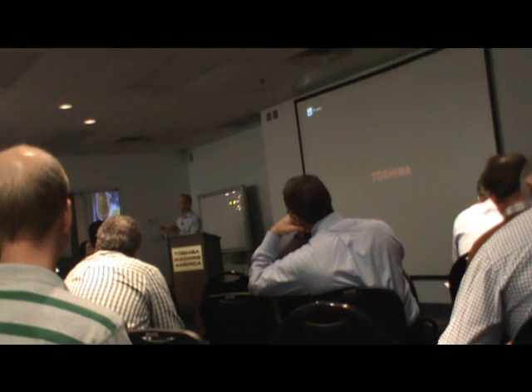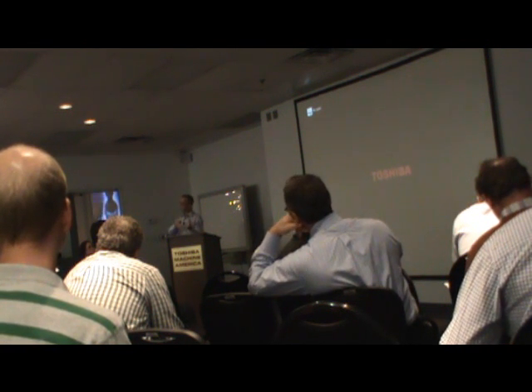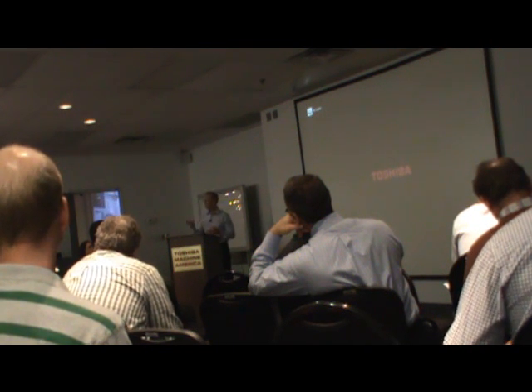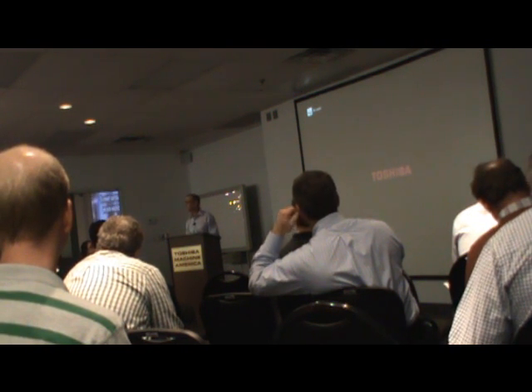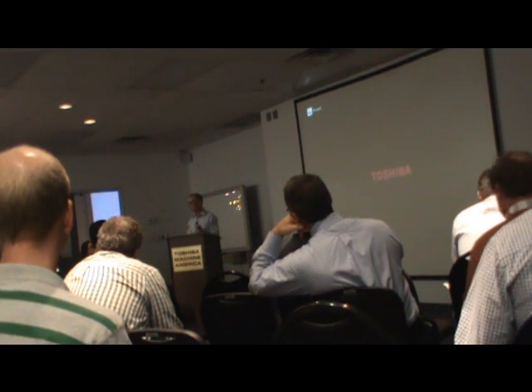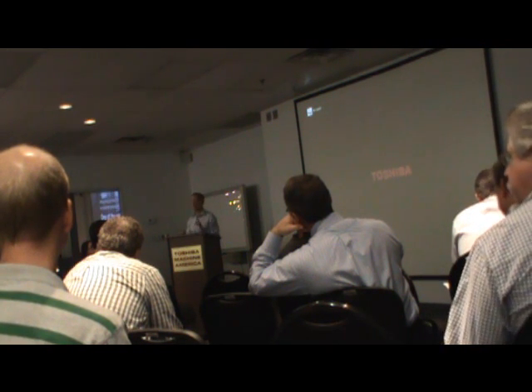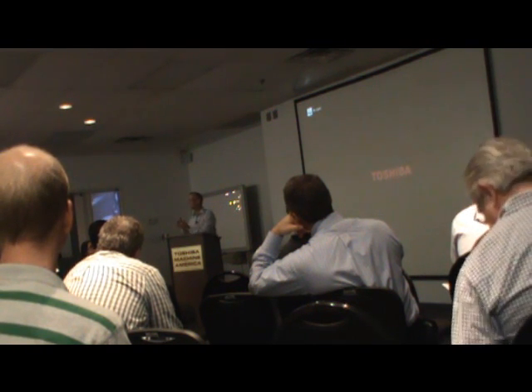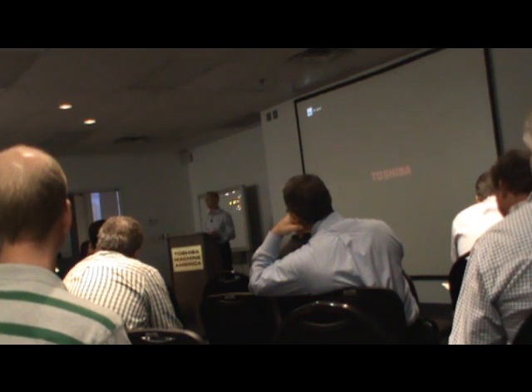But to go back, if you hard coat that and you're at 54, 56, 60 Rockwell, and P20 you're at 28 to 32 Rockwell, that helps you right there, but you do need to make sure that you're monitoring visibly and also dimensionally the hard coat, because it does wear. I will say on a two cavity, the part is back here, apologize, it's a two cavity that ran about 330,000 parts, we have had to strip that and recoat it, and it was primarily in the straight spline area, because there's no draft. And it is on 33% glass fill, but that's a different situation. But it boils down to whether it's a P20 tool or hardened steel, you still have to monitor.